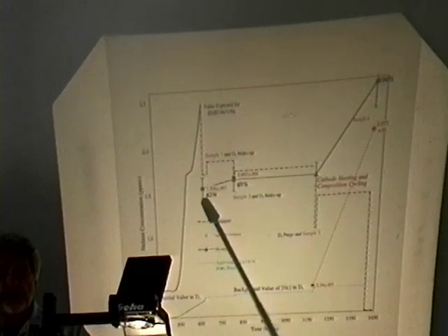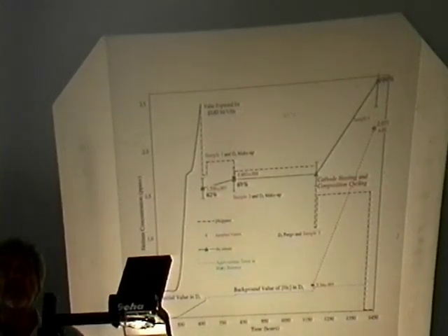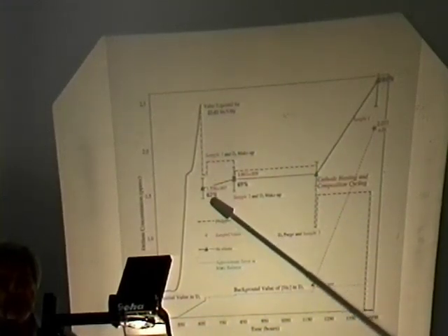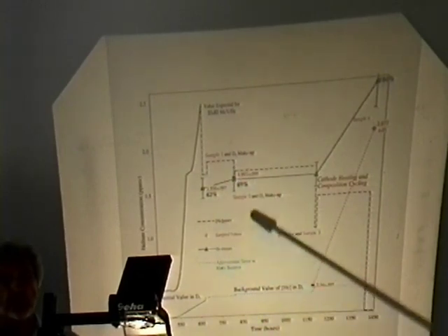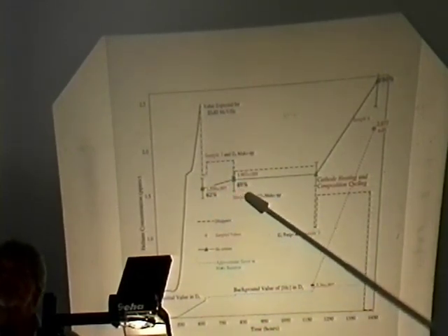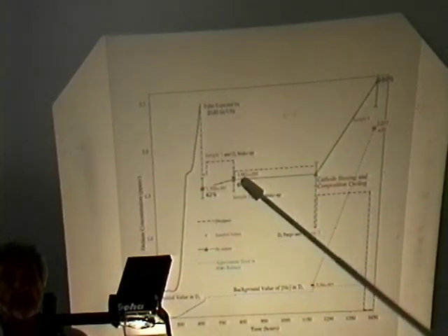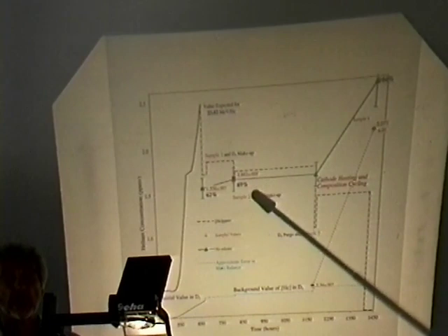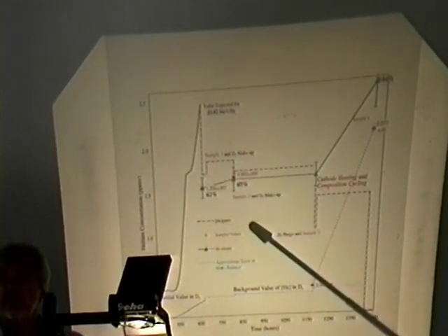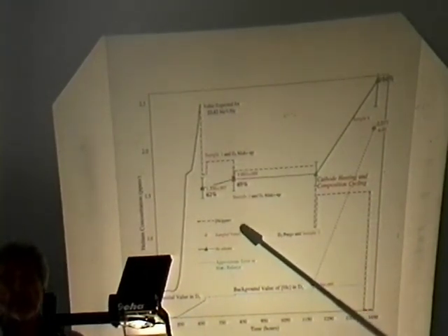So we took a sample of this, quite a large sample, submitted it for helium-4 analysis, and then made up the volume of gas that we'd taken from the cell with fresh deuterium containing 0.34 parts per million. So, in fact, we had diluted the gas. We expect the second sample to have a lower value of helium-4 than the previous. What we in fact observed was that the helium-4 signature had increased rather than our expectation of it having decreased.